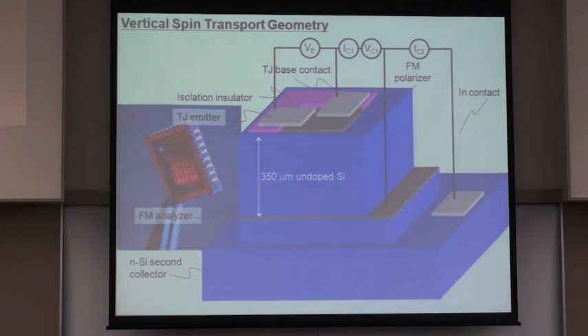Okay, so one of the device geometries that we've employed to realize the band diagram that I've just shown you is a vertical geometry device. We've also applied this to lateral geometry devices in which we can, for instance, add another electrical contact, an electrode for electrostatic gating, in which case we can investigate the role of interfaces on the spin transport. But in this simplest geometry, what we do is